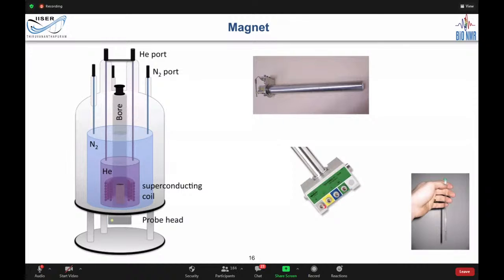There are actually 4 frequencies here. So you can put it right inside. This long tube goes up here. This is actually at room temperature, not at helium temperature, because this bore is there. The superconducting magnet coils are wound around the bore. Once it's charged, it's permanent. It's a superconducting magnet. It doesn't lose its magnetization as long as you don't do anything with the helium mass. Anyway, the sample goes from the top and lands in the middle of your probe and the middle of your magnet here.